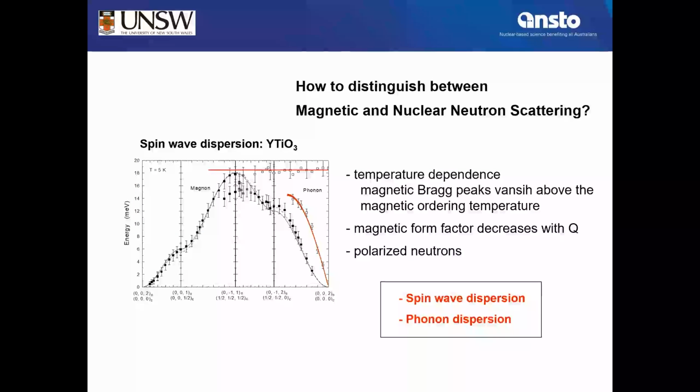This is an example, yttrium titanate. The black curves are indeed the magnons, the spin wave dispersion. And now I can really take a ruler here and determine that the direct magnetic exchange interaction is about 6 meV, 5.8. So that's really fantastic. Okay, but back to the puzzle.